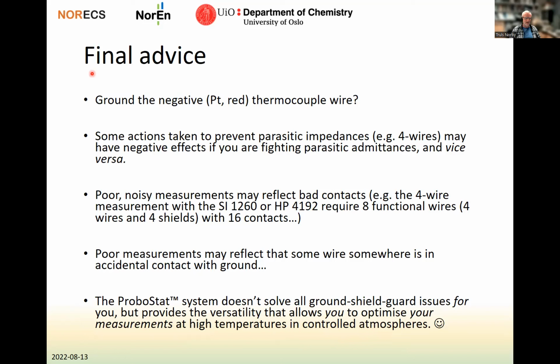So with that, we close with a few final advices. When you have done everything properly with a ProboStat and you have gotten rid of all the noise and everything, maybe by a metal outer tube, and you have grounded everything, you have one possible error left, namely the thermocouple. The thermocouple comes into the ProboStat from your temperature controller or temperature readout unit. And this thermocouple may act as an antenna that picks up noise on the outside and feeds it into the sample area. To get rid of this, you can try to ground the negative platinum thermocouple wire. This is usually not a problem for the temperature controller or readout unit, but it effectively removes signals coming into the sample from the thermocouple.